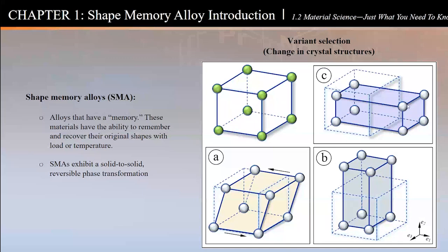You can see 1 or 2 or up to 12 in some cases, or 6, depending on what that symmetry looks like. And that's important, because one cubic phase can go to many different variants of these lower symmetry phases. And that's what we refer to as the martensite. If you look at martensite and austenite: the high temperature phase, called austenite, is cubic. The low temperature phase is called martensite, and it could be some other structure like this rectangle here, which we call